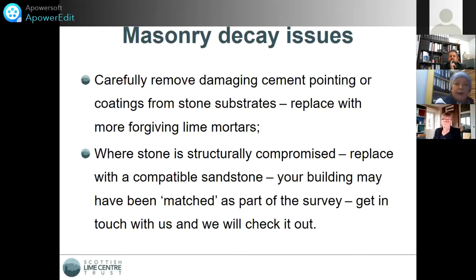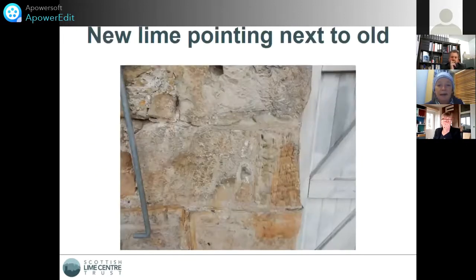So ideally, we want to carefully remove any damaging cement pointing or coatings from stone substrates and replace them with more forgiving lime mortars. And where stone is structurally compromised, replacement with a compatible sandstone would be in order. And it may be that your building has been matched as part of the Inverkeithing survey, and that should be available in the public domain on Fife Historic Buildings website. And we can see that we've got new lime pointing here next to old, and with a fairly good match. It's not in your face and it's the right material.